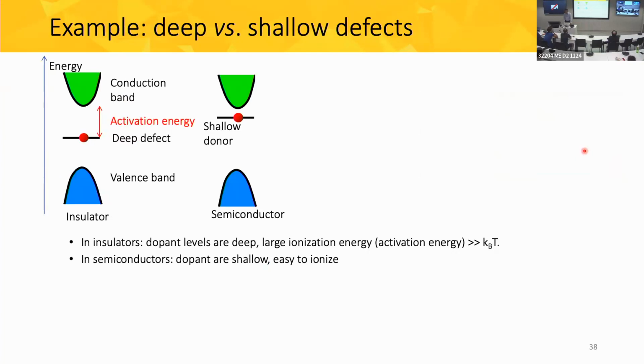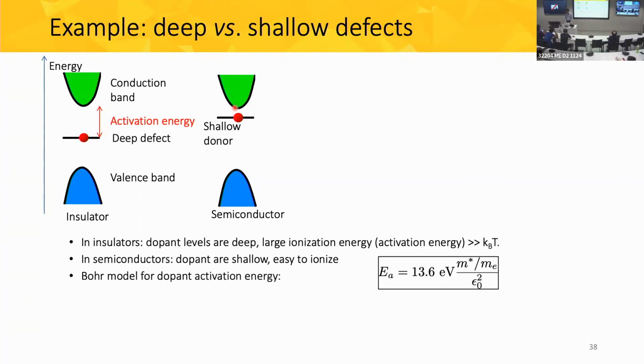To answer this question, let's look at the difference between an insulator and a semiconductor. So in insulators, the dopant levels are deep, and the energy you need to pay to ionize them is high, much more than kBT. So you end up with an insulating behavior. In contrast, in semiconductors, the dopants are shallow, and they're easy to ionize and give you electrical conduction within the band. A simple way to think about the activation energy is through the modified Bohr model, where you take the 13.6 eV from the hydrogen atom, you multiply by the effective mass and divide by the dielectric constant squared.